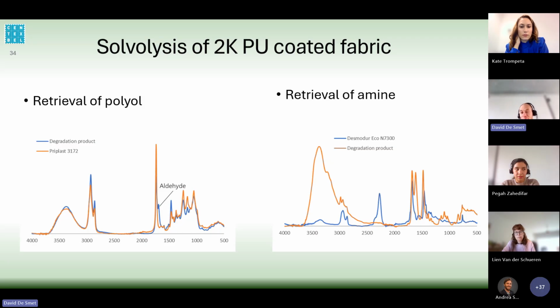For instance, in the blue line, we can see that we have a peak at 2250, which is the isocyanate peak. Of course, this is gone. But on the other hand, we can see that there's a peak arising above 3000, and this is typically for amines. We also see peaks at 1550, which is typically for primary amines. Taking all those peaks into account, we can conclude that we retrieved the primary amine of the isocyanate which we used to make our PU coating. So we were able to retrieve our amine in high purity. We also were able to retrieve the polyol which was originally used, but we had some impurities because we had some oxidation of the polyol into aldehyde.